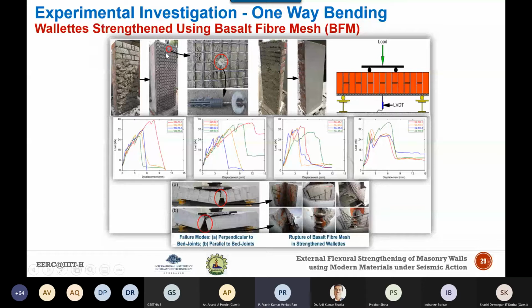Now, in this test also, you can see that all these specimens have failed in flexure. Here the intermittent drops and the strength gradients, which are indicated by the local peaks in the load versus displacement curve, are due to the sequential failure of individual fiber yarns and redistribution of tensile forces to the intact yarns. So the wallettes ultimately failed because of the rupture of the fiber mesh. However, debonding of the fiber mesh from the masonry has not been observed. So apparently, the mechanical anchors are very helpful in the good bond of the basalt fiber reinforced cementitious matrix with the masonry.